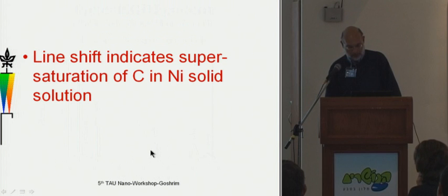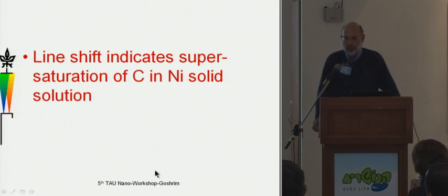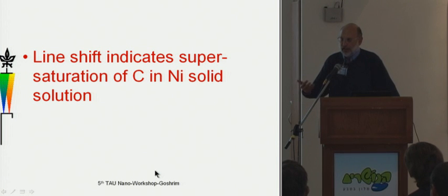And we believe that the explanation is that we have a supersaturated solid solution of carbon within the nickel. In other words, far more than the equilibrium solubility enters due to this very fast non-equilibrium process of quenching, on I don't even know what time scale.